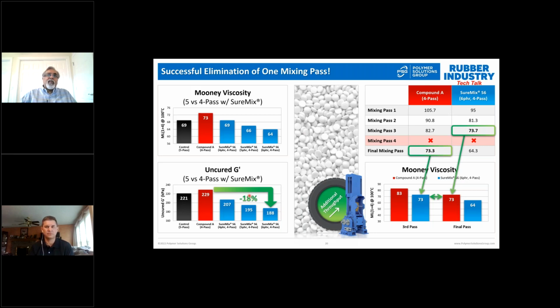So our work in the lab, and then further in the plant, was to focus on the 4 PHR mix, take baby steps rather than a leap of faith, and try to save as much mixing time as you can. We do have customers who have taken 2 mixing passes out in some silica compounds, taking full advantage of the viscosity reduction of SureMix. But even if we look at the Mooney, we can see with the 6 PHR, we could very easily take 2 mixing passes out. But even 1 mixing pass out is a throughput increase of 20%.